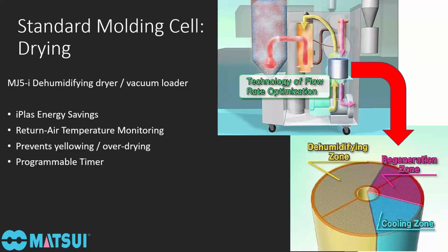Desiccant bead type dryers, resin material manufacturers will recommend drying time based on desiccant bead technologies. They'll be somewhat conservative in their estimates because they don't want to get calls from customers thinking there's a problem with the resin when actually it's a dryer problem. So their drying recommendations for the different materials will be somewhat conservative, and they're based on the desiccant bead technology. Where because of our desiccant rotor, because of the low and stable dew point, we can pull more moisture out of the air. We can dry most materials in about 2 hours.